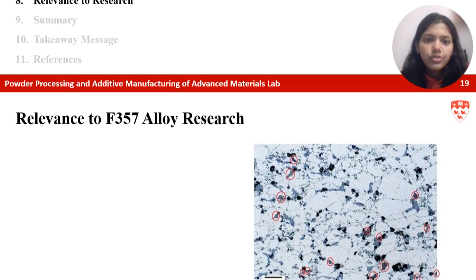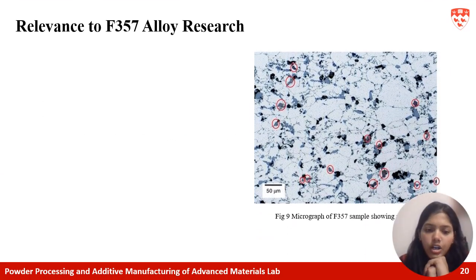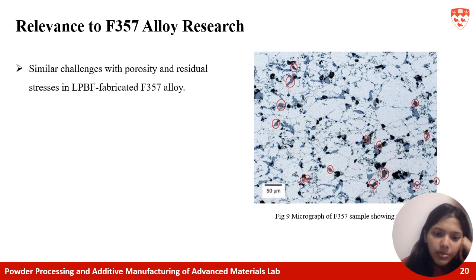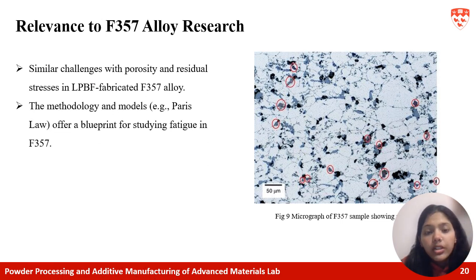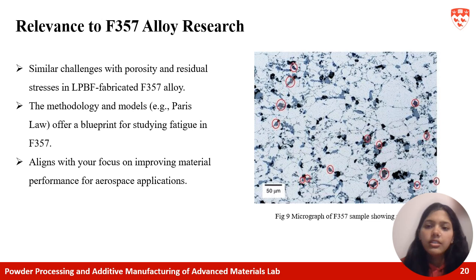Moving on to the relevance of this paper to my research. My research focuses on minimizing microstructural differences in aluminum silicon 7, which is rather similar to aluminum silicon 10 produced by LPBF. One key challenge is the trade-off between strength and fatigue performance. So the work that they presented in the paper aligns closely with my focus on defect reduction through optimized heat treatments. The findings validate the need to study crack initiation sites, especially in downskin regions where defects are more prevalent.